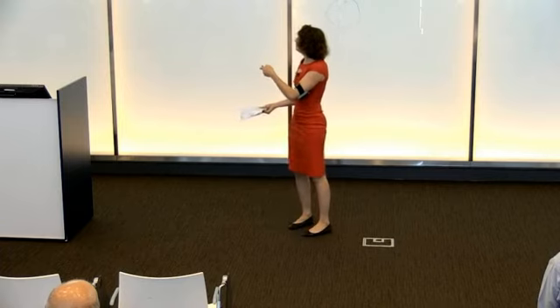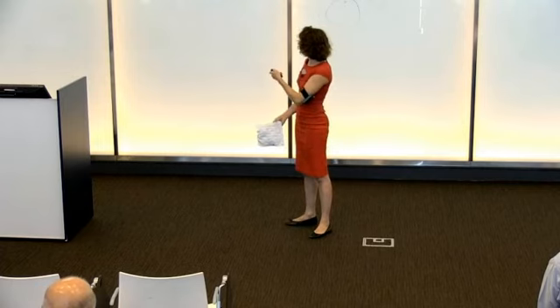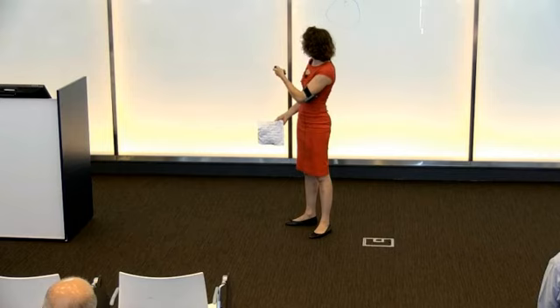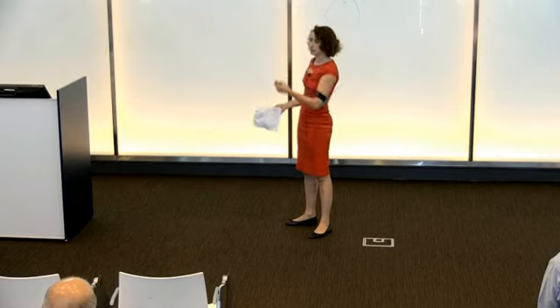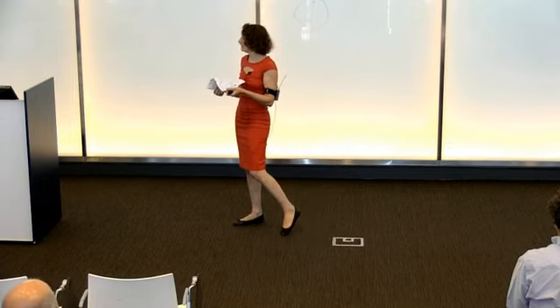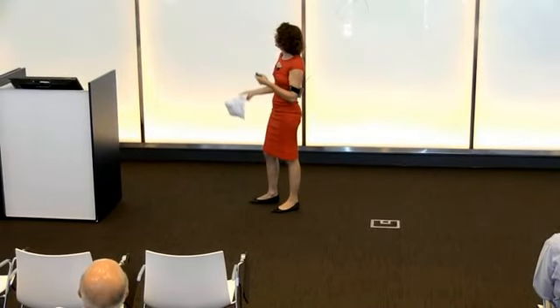But in the first case, each time I force the middle node up, it obtained a new configuration. And in the bottom case, you can see that it's different because here I have plateaus and jumps, plateaus and jumps. So not every time you force the system up, it will attain a new configuration. And this is exactly what we wanted. It's another way of showing that this system has some rigidity or some effective bending curvature in a way. You force it, it will not always go to a new shape.